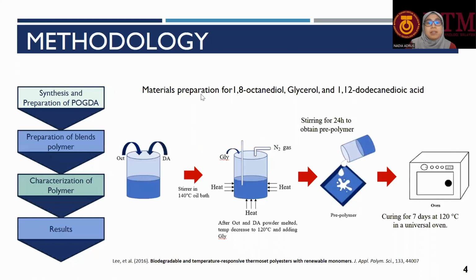So here is the method to produce the POGDA. At first, the diols and diacids are stirred together at 140 degrees Celsius under nitrogen condition. After the monomers are melted, the temperature is slightly decreased to 120 and glycerol was added. Then the pre-polymer was formed in a mold, then later on cured in an oven for 7 days at 120 degrees Celsius. So these are our findings for this preparation of POGDA.